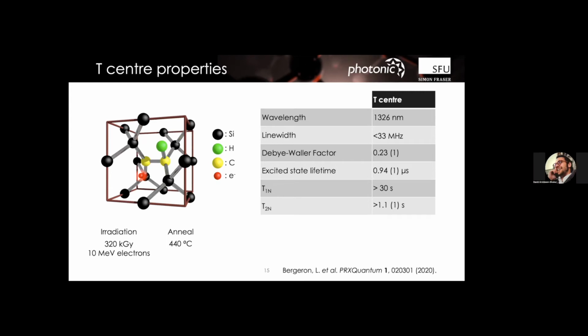Yeah, great, Stephanie. So we have a question from Daniel Jackson, and he's writing, could you please expand a little on the origin of the splitting between the ±3/2 and ±1/2 hole states? Yeah, fantastic. So it is to do with the actual native strain around a T center. Whenever you create one of these defects, the lattice has a very predictable strain pattern around it because of the defect. And that gives rise to, like I said, strain splitting for the actual valence band around it, essentially, and that's what the hole is seeing, right? So you actually get this inherent strain splitting, and you get different ones for different defects. So yeah, I hope that's the direct answer.